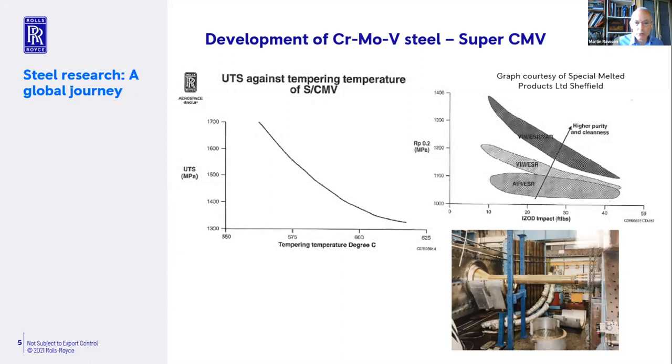We reflected that in the specifications — not only pushing the strength level to a higher UTS, but also imposing much lower acceptability levels for so-called tramp elements such as phosphorus, sulfur, tin, and antimony. Those elements are known to embrittle the material through effects like temper embrittlement. When tempering at a lower temperature, tramp elements can precipitate at grain boundaries and cause embrittlement. So inclusion control is good for fatigue properties, and reducing tramp elements is good for reducing embrittlement.